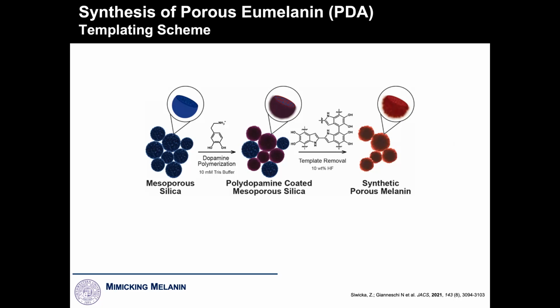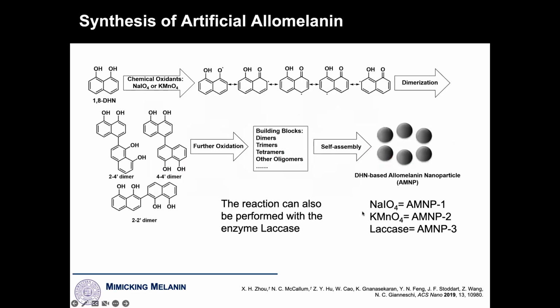In parallel, I had a grad student, who has also graduated and was excellent, who worked together with two other grad students who graduated as well, on Allomelanin. This is the one that I told you about earlier that doesn't contain nitrogen. We worked out how to take this precursor molecule and essentially cross-link it through a radical reaction. So a little bit of organic chemistry for you. We generate a radical. That radical can be spread into the ring through resonance, so the radical is stabilized by this kind of structure, as you know. And it can then react at these different positions. So we can make all kinds of dimers, trimers, tetramers, and that's how the cross-linking works. So there's some radical chemistry in action for you.